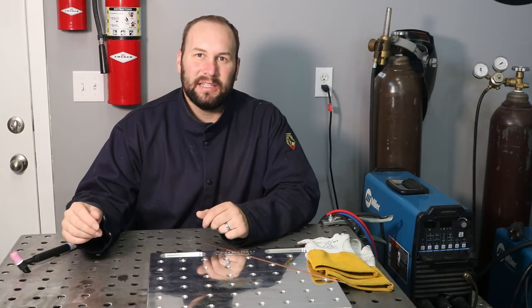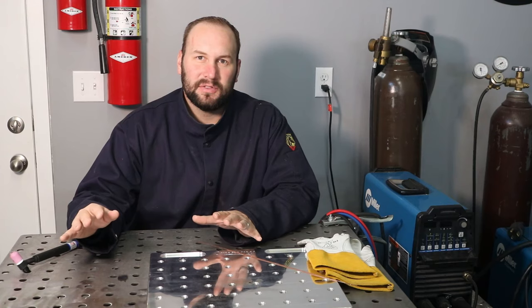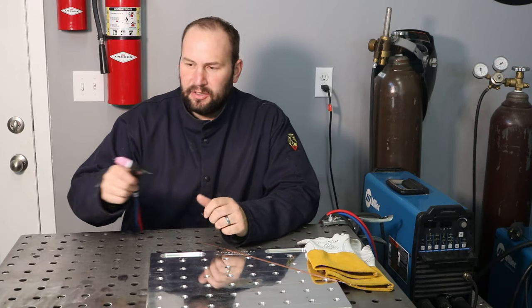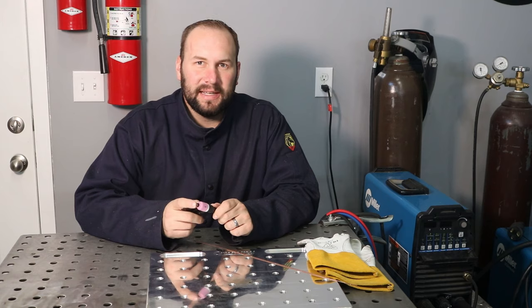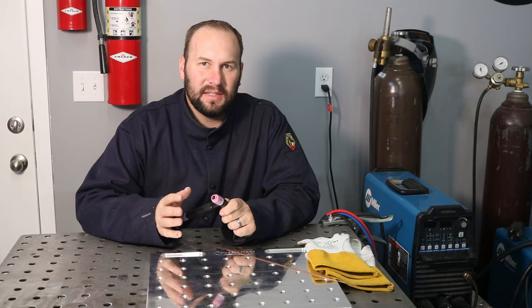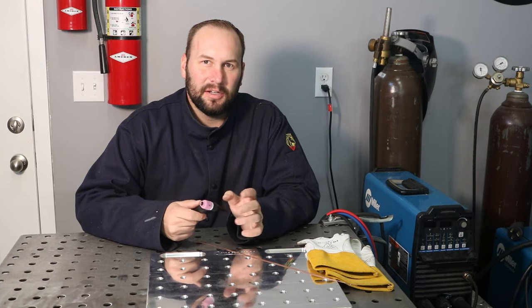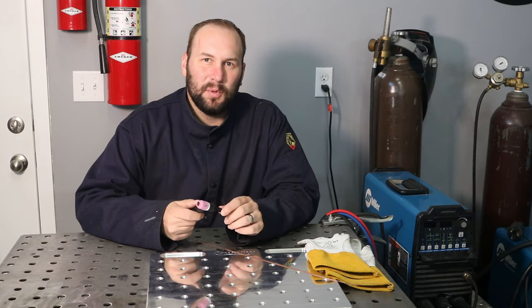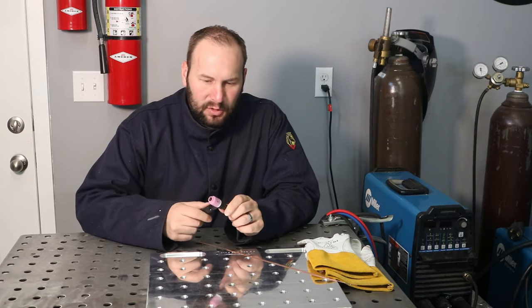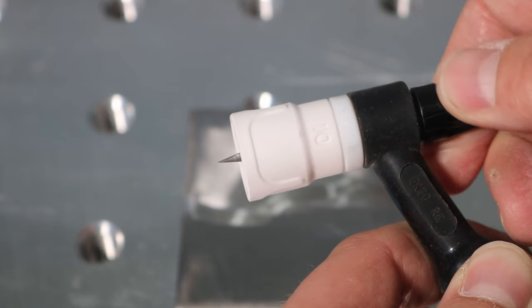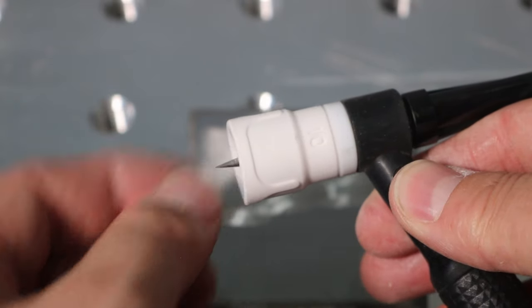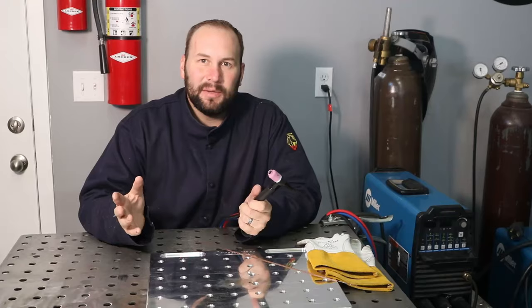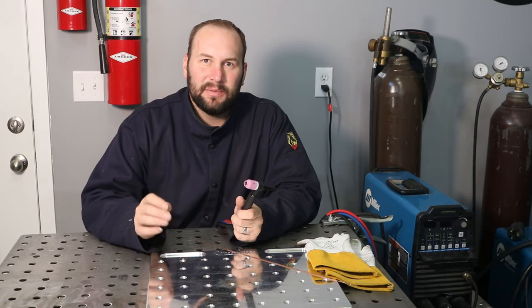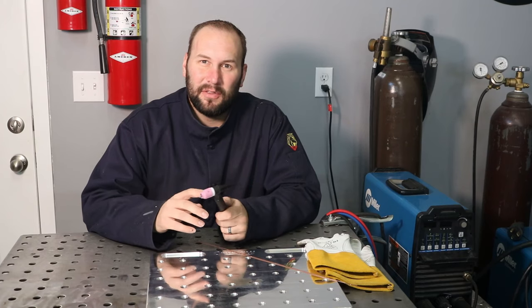Now, once your material is clean, you want to make sure and set up your torch, and we went over how those go together, but in general, you want to grind your electrode with a nice point on it, and I wouldn't worry too much about the angle on the point as you get started. You know, there's a little bit of a difference between different angles and how big your cone gets, but I won't worry about that at this point. So go ahead and put it in your torch, and if you're using a regular cup or a gas lens like this, I'd have it protrude out, stick out about a quarter of an inch. I'm going to be using a little bit larger cup with a gas lens just to make it easier for you to see for this demonstration, so I'll let mine stick out just a little bit further than that.